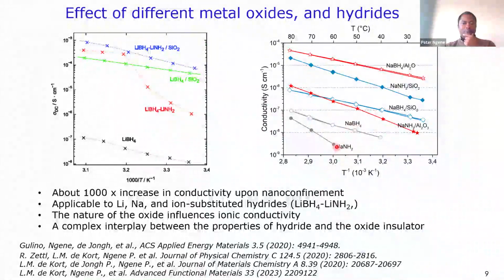Now, if I put my sodium imide in alumina, I have this increase in conductivity. If I put the sodium imide in silica, you see the increase in conductivity is much, much higher for silica. Now, if it is sodium borohydride, the only difference is that the anion here is different. If I now put my sodium borohydride in silica, I just have a very small increase in conductivity. But if I now put it in alumina, the increase in conductivity is much, much, much higher. So it's a reverse case for sodium borohydride and sodium imide.